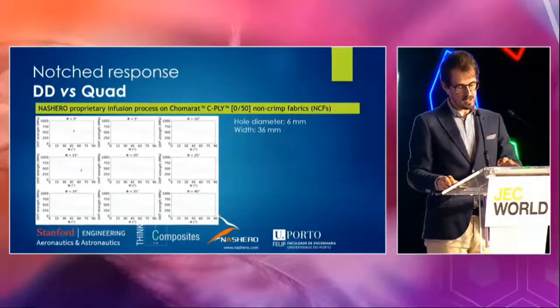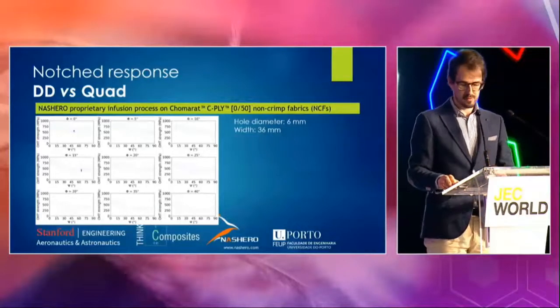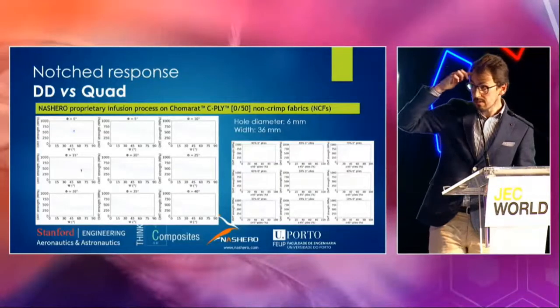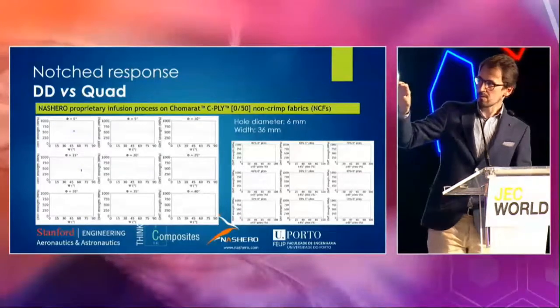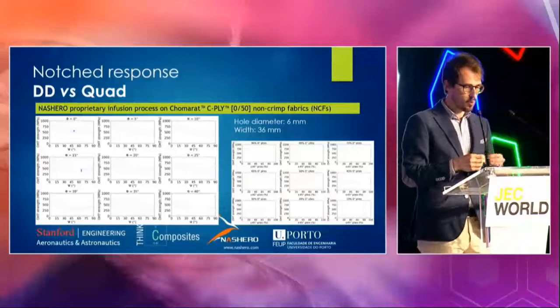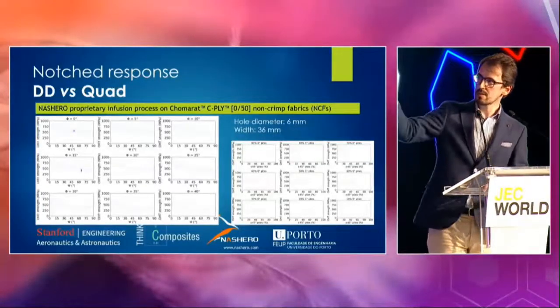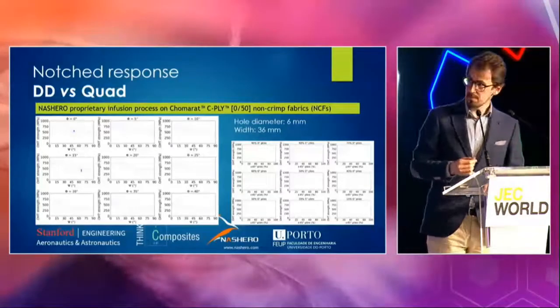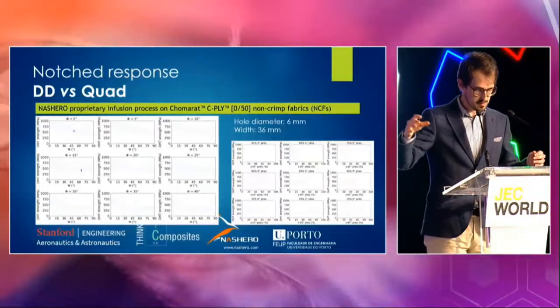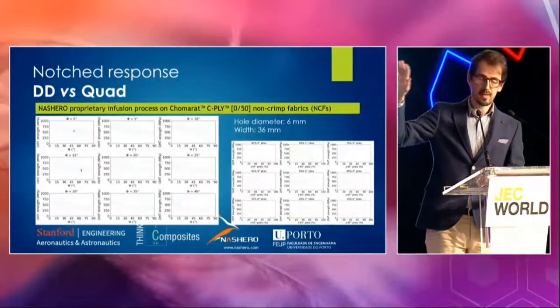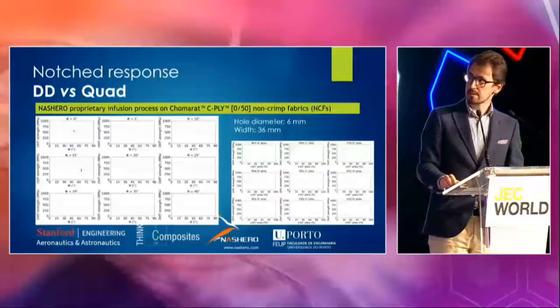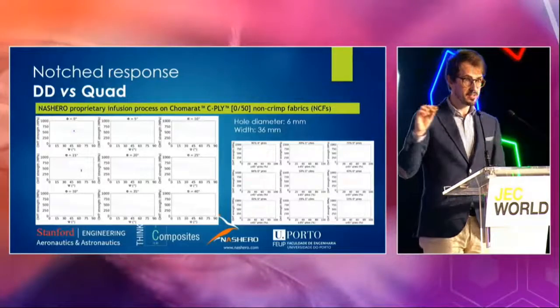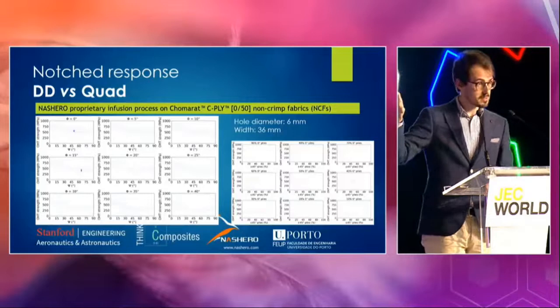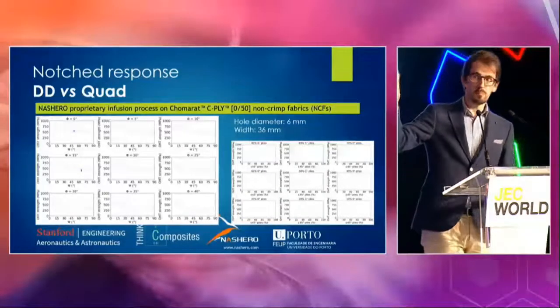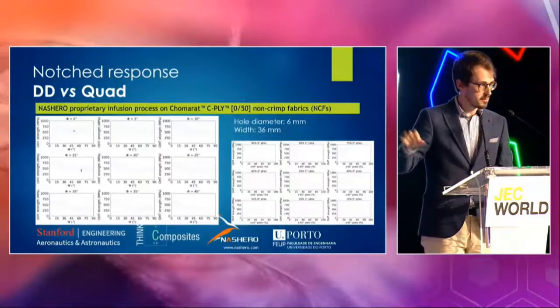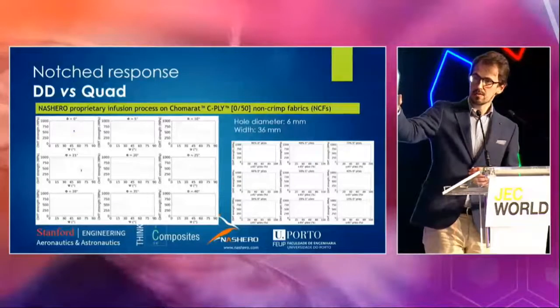And the question that you can make then is, how would this compare with the notched strength of quad laminates, for example? I did the same exercise. Unfortunately, the colors probably don't show very well. But what you see now on the right is the same exercise, but considering the typical way of discretizing legacy quad laminates, in terms of percentage of 0-degree plies, 90-degree plies, plus minus 45-degree plies, and you can see that in terms of notched response, you can actually match the notched strength of quad laminates with double-double laminates. Nevertheless, I should call your attention to the fact that although the plots on the right are continuous, remember that quad are not continuous. So actually, many of the solutions that you see there on the right are unfeasible from a layup or lamination point of view, whereas the ones on the left, all of them are feasible.